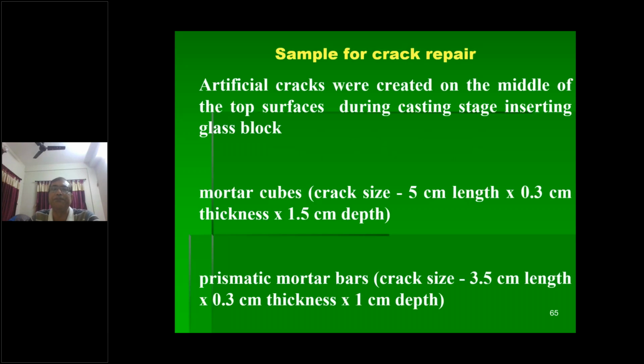Next, we have started with how this mortar, or this system, can be improved for crack repairs. So what we have done in these cases, we have made some artificial cracks on the concrete samples, both in mortar cubes, where the crack size is 5 centimeter length, 0.3 centimeter thickness, and 1.5 centimeter depth. In a prismatic mortar, also, the crack size is 3.5 centimeter length, 0.3 centimeter thickness, and 1 centimeter depth.